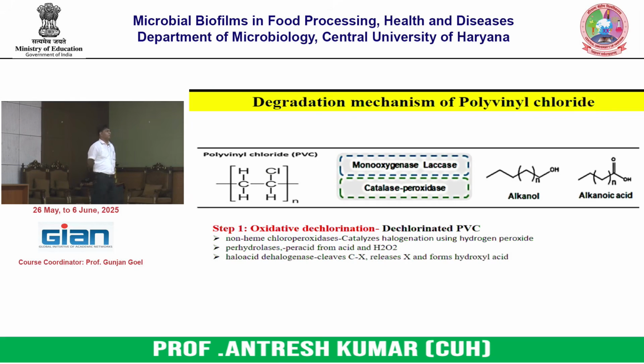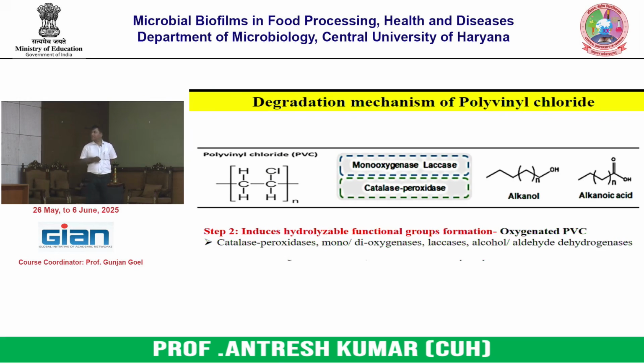So the first step for the degradation of PVC is oxidative dechlorination, the removal of chlorine first, so that the chlorine position can become a hydroxyl group, which ultimately tends to reduce the hydrophobicity of the PVC. The second step is oxygenated PVC, where the oxygenated oxide groups increase, which increases the hydrophilicity of the PVC and can make it vulnerable to degradation.